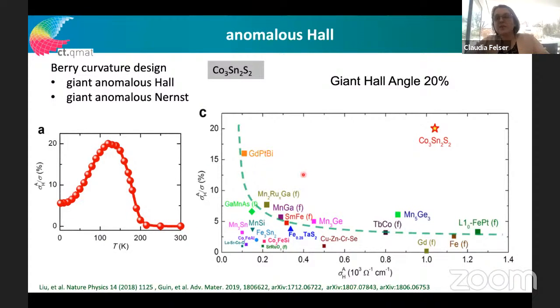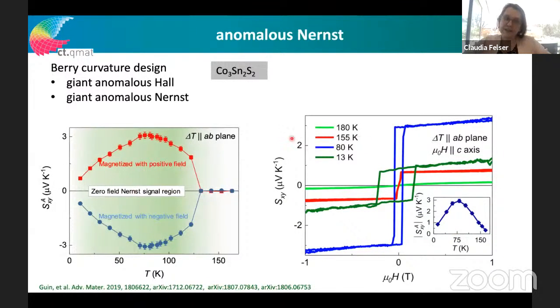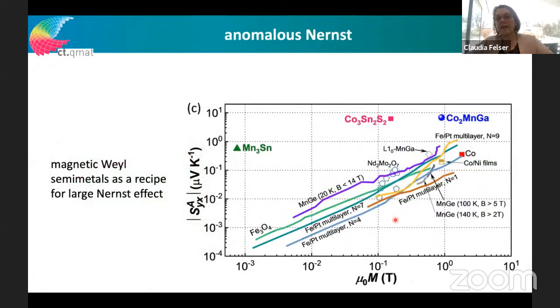And you see again, so compared to all the other magnetic materials here, like the Hall effect versus the Hall angle, it stands out, very similar to also the manganese 3 compounds and so on. Okay, and again, we have a very large Nernst effect here now. We can make a hysteresis. Also here, it's at zero field, a large Nernst effect. This is nice because of the hard magnetic behavior of the material. And again, it's not comparable to the standard material. It's due to this extra contribution from the Berry phase, it's much larger, the value, compared to all the standard magnetic materials.